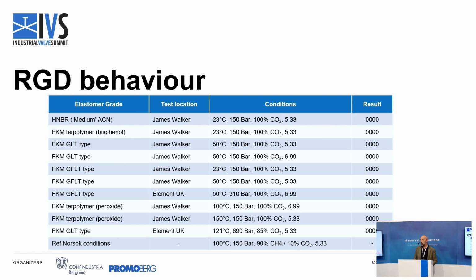If we look at these results, there are a lot of elastomers that we tested with 100% CO2, and in order to have the perfect result of 0,000, which is the best result you can have for the NORSOK M710, we had to lower the temperature of the gas. We also have some elastomers that actually pass the NORSOK M710 test with 100% CO2. This is a direct consequence of the capability of carbon dioxide in the supercritical state to enter the elastomeric compound.